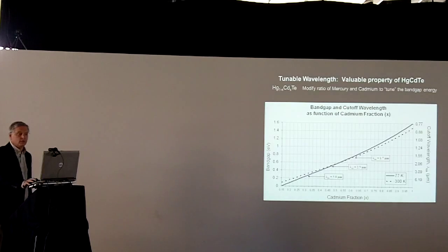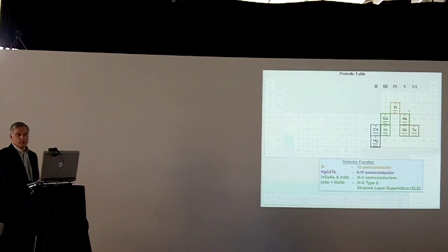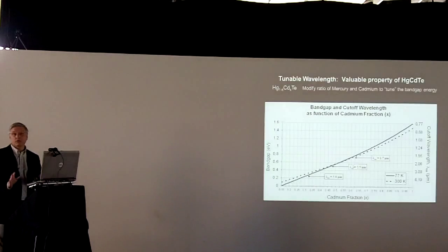And certain materials, like InSb, which is one indium atom and one antimony atom, you can only mix 50-50 and it always has a set band gap. Silicon has a set band gap, but with mercury cadmium telluride, you can change the mixture of the mercury and cadmium to change the band gap, which changes the cutoff wavelength. So always 50% of the atoms are tellurium. If you look up here at the formula, 50% is tellurium, and the other 50% are specified by the cadmium fraction. As you increase the cadmium fraction, that's more of the atoms are cadmium, you will increase the band gap, which reduces your cutoff wavelength. So you need stronger photons or shorter wavelength photons to release an electron from the grip of the crystal lattice. Or as you add more mercury, you make a smaller band gap and you can go for longer wavelengths.